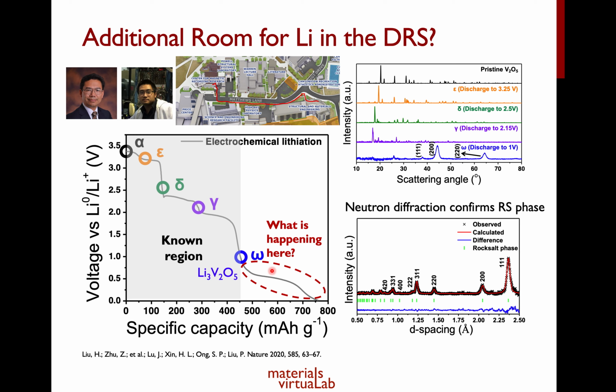So they actually confirmed that this is indeed the disordered rock salt using both XRD experiments as well as neutron diffraction. Okay, and they confirmed that essentially during this entire additional capacity that you see below 1 volt, you still have the rock salt phase.